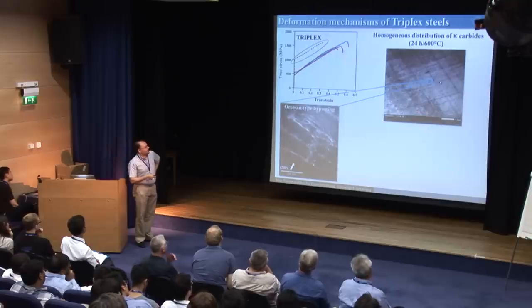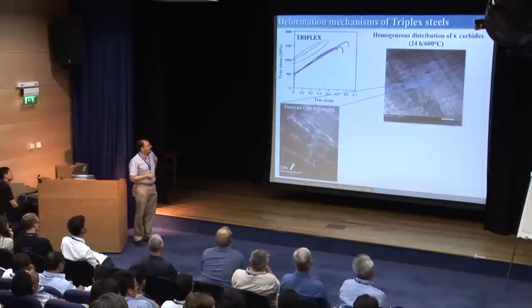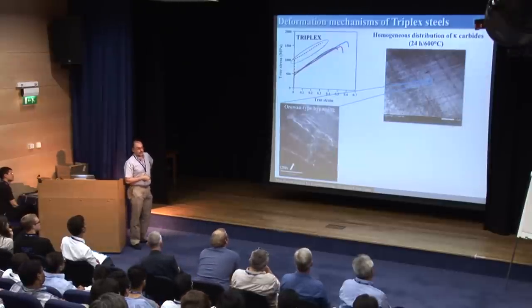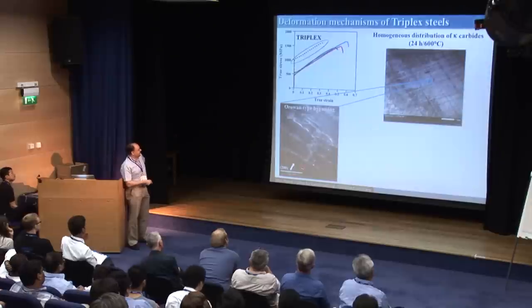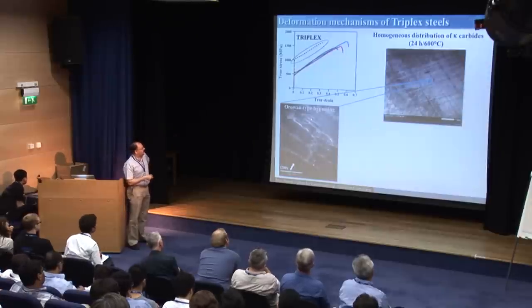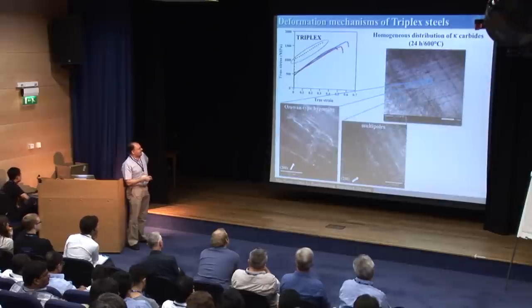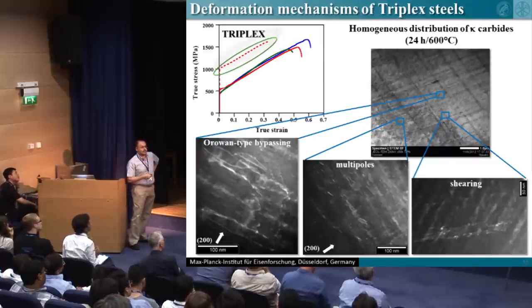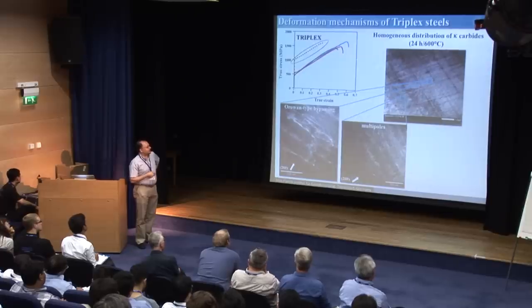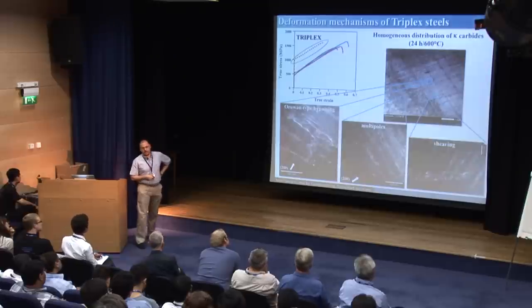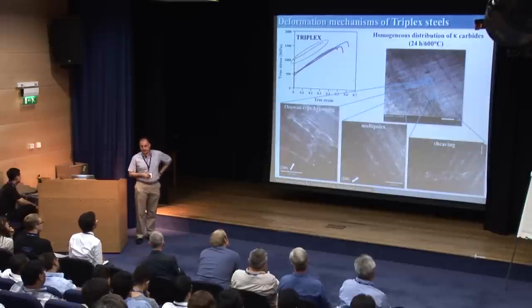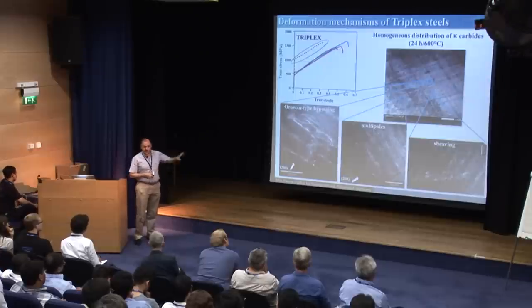This is quite complex because this is an STEM image where we can see all these low angle grain boundaries, dislocation patterns. When one takes a look at the different areas of this microstructure, this is our weak beam TEM images. We can nicely see one type of bypassing here. In those low angle boundaries where dislocation density is higher, it cannot be nicely seen here, but we have mainly multipoles, which is an indication that cross slip is mainly enabled in these areas. And also we have shearing of particles localized, but this mechanism is not relevant for this microstructure.